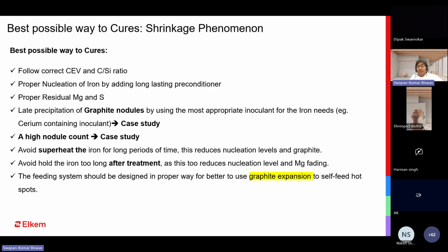Also, control the residual magnesium and sulfur level. You need to check the nucleation by adding a long-lasting preconditioner, which will help to maintain the nucleation level for a longer time.